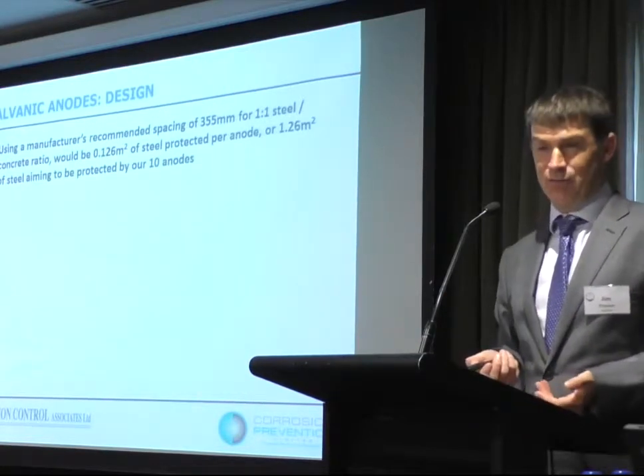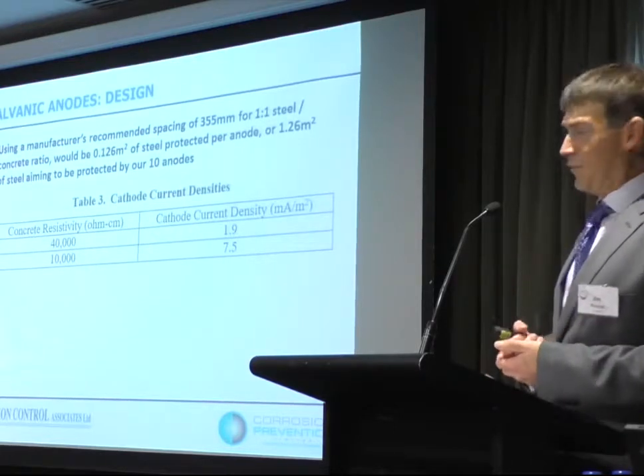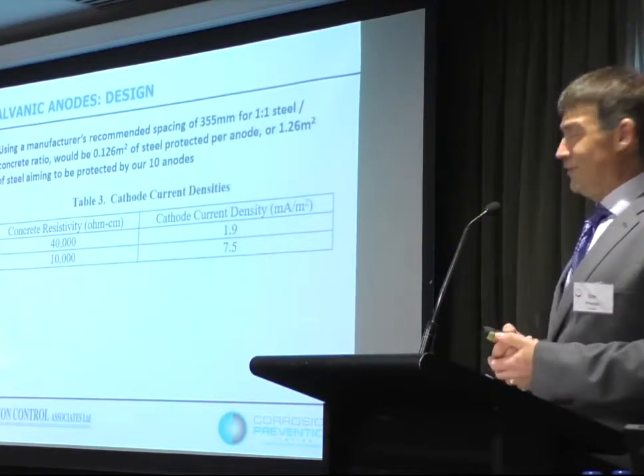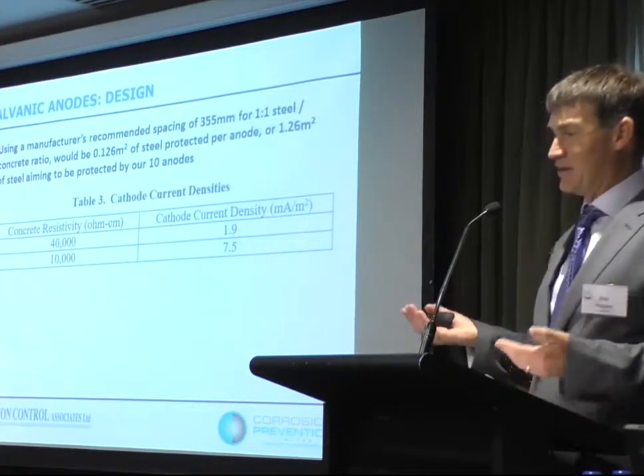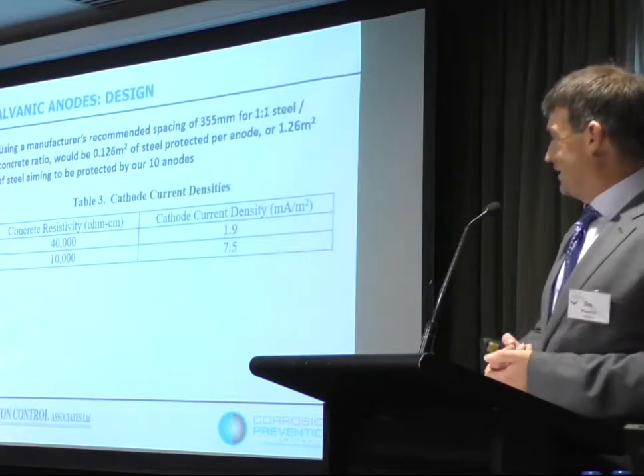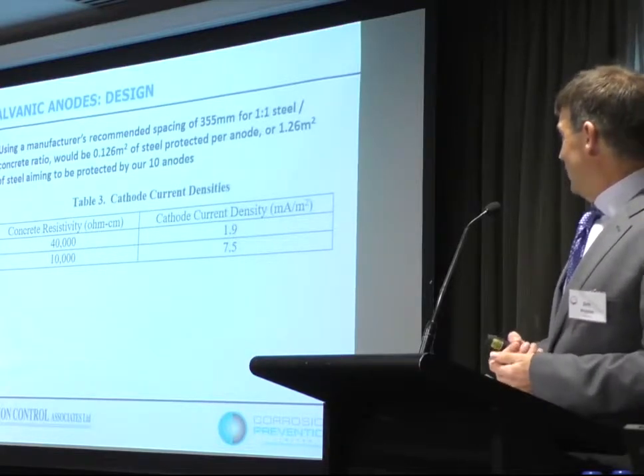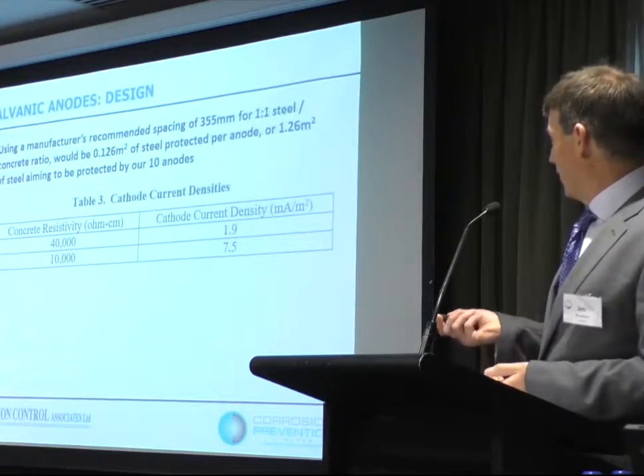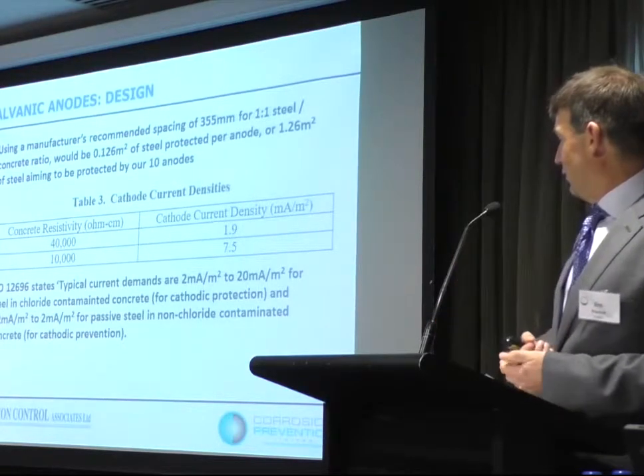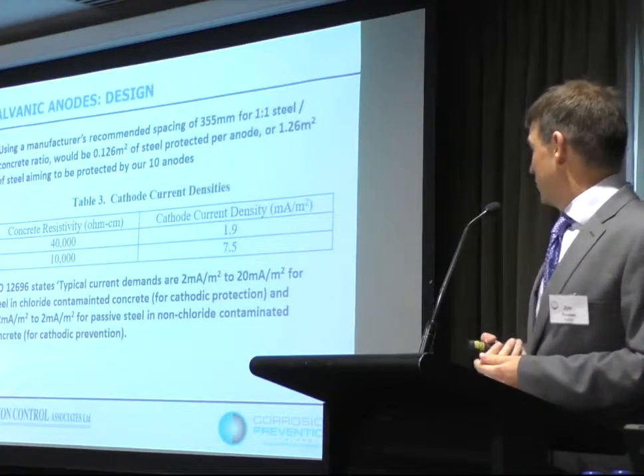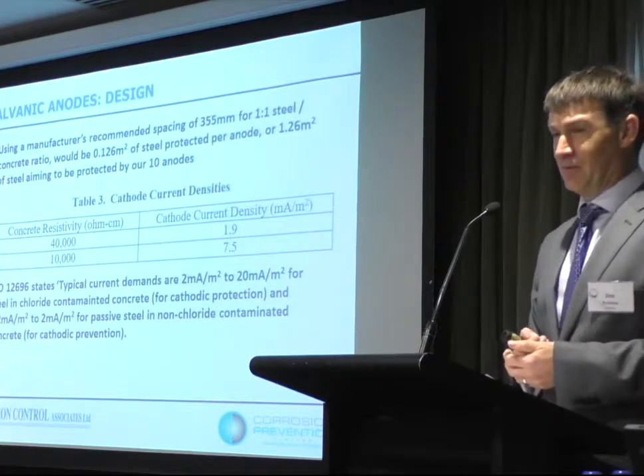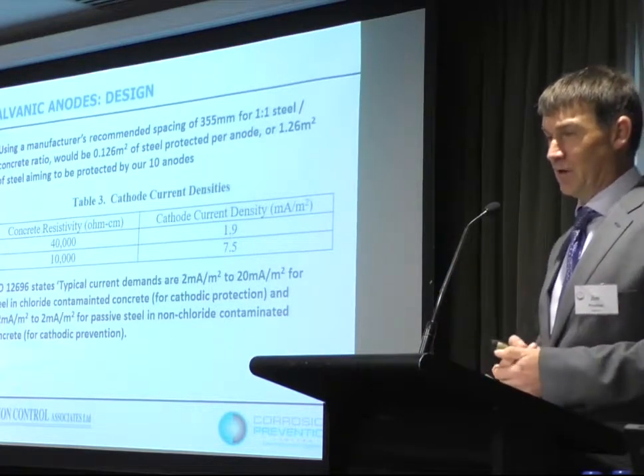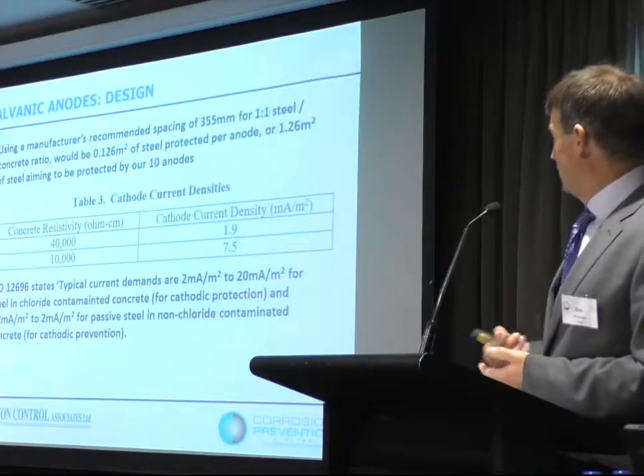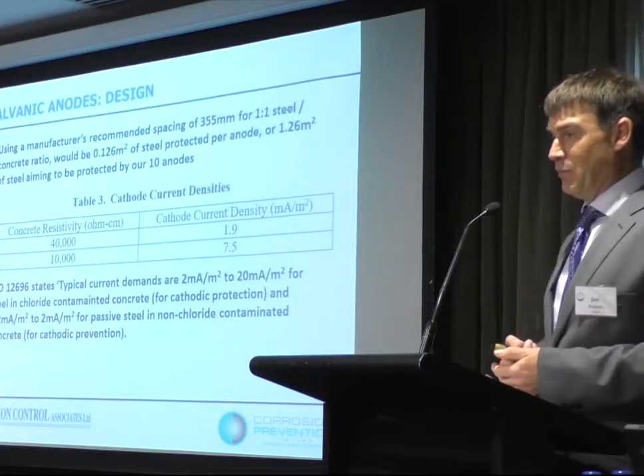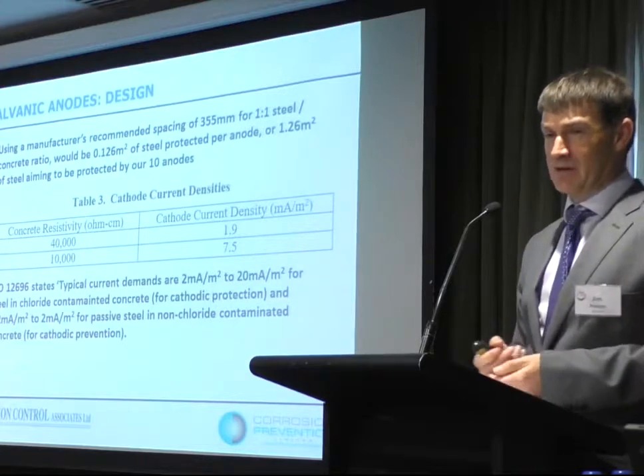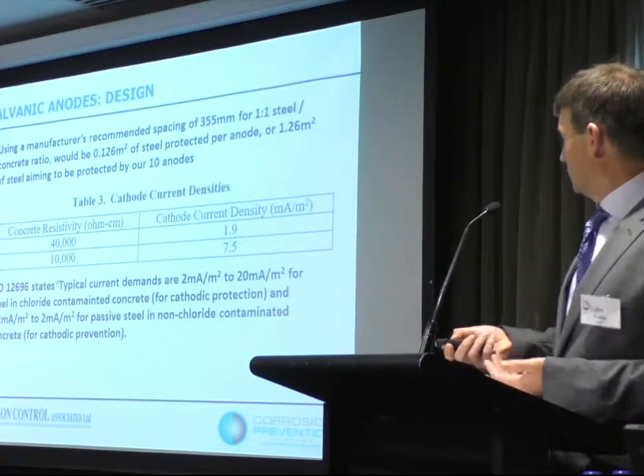So what sort of cathode current densities would those give us? If we've got 10 anodes and they're a typical spacing of 355 millimeters, that's 1.26 meters squared of steel we're looking to protect. If we say a simple one-to-one steel-concrete ratio, so at 40,000 ohm centimeters, we get a cathode current density of 1.9 milliamps per square meter. And our standard says that if we're getting between 0.2 and 2, we're getting cathodic prevention for steel that's not yet corroding. So we're achieving that. We can do that with galvanic anodes. And if we've got a low resistivity, then we can do a bit better than that. We might be getting close to meeting a cathodic protection criteria. So that seems quite interesting.